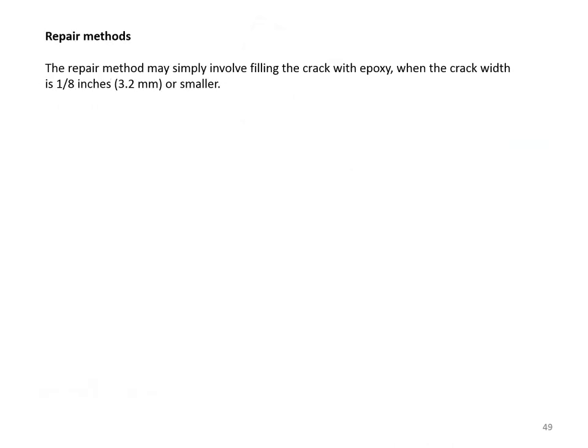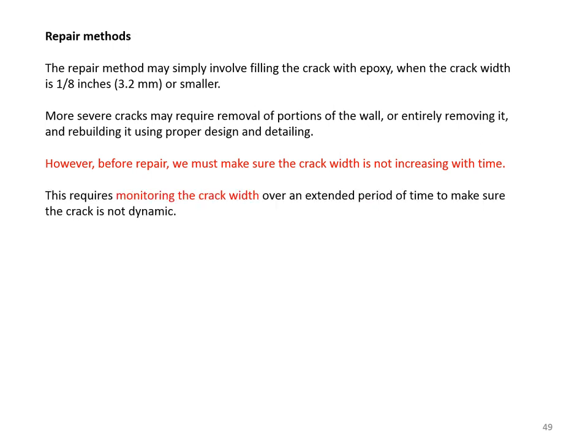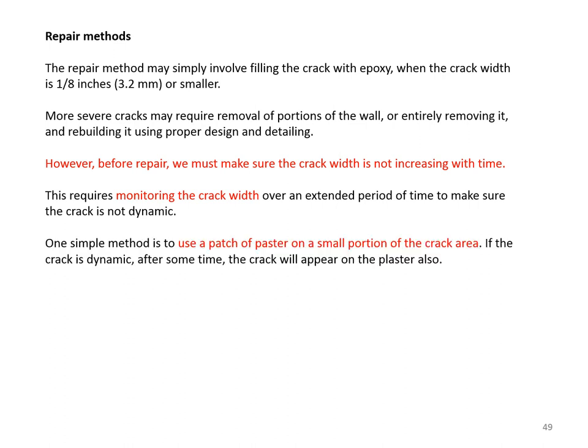Repair methods: the repair method may simply involve filling the crack with epoxy when the crack width is 1/8 inch or smaller. More severe cracks may require removal of portions of the wall or entirely removing and rebuilding it. Before repair, we must ensure the crack width is not increasing with time—this requires monitoring over an extended period.